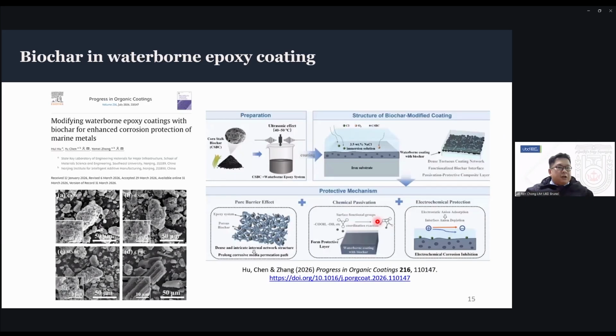And more recently, we also see biochar being used in waterborne epoxy coatings. Waterborne coatings are becoming popular today as they emit less volatile organic compounds compared to traditional solvent-based coatings. But there's a problem with waterborne coatings: normally they have reduced mechanical strength, and when they dry out, when the water evaporates, they introduce a lot of defects and pores inside the epoxy resin.